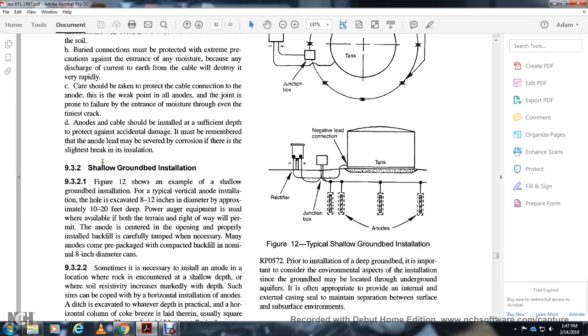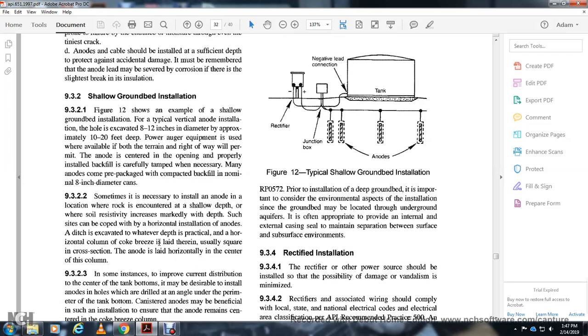9.3.2 Shallow ground bed installation. Figure 12 is an example of a shallow ground bed installation, a typical vertical anode installation with a hole of 8 to 12 inches in diameter, approximately 10 to 20 feet deep. The anodes are centered in the opening and properly installed with the backfill, carefully placed. The anodes may also come pre-packaged complete with the backfill, with a nominal 8-inch diameter.